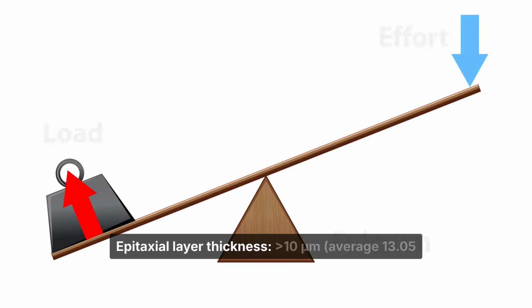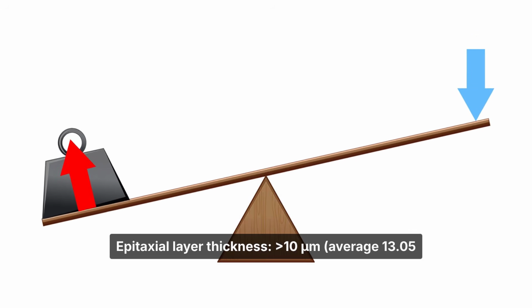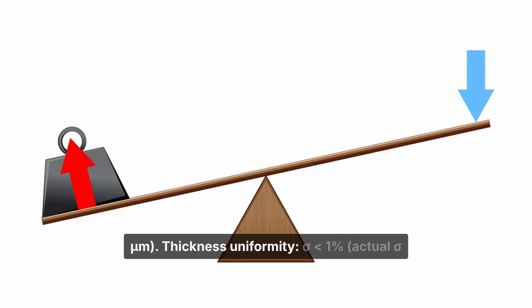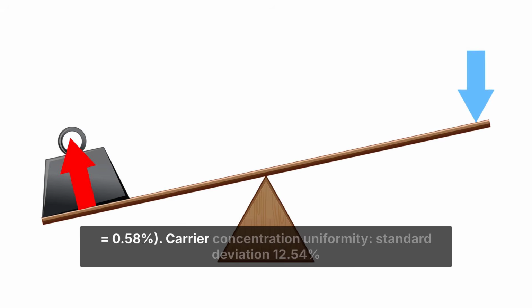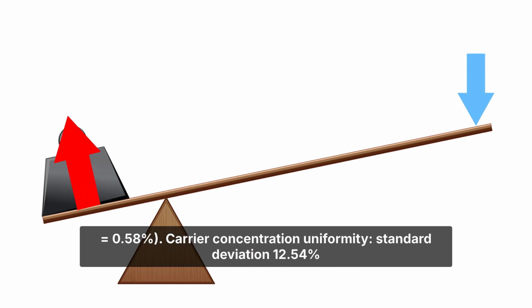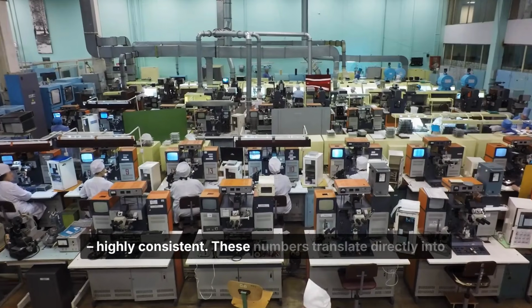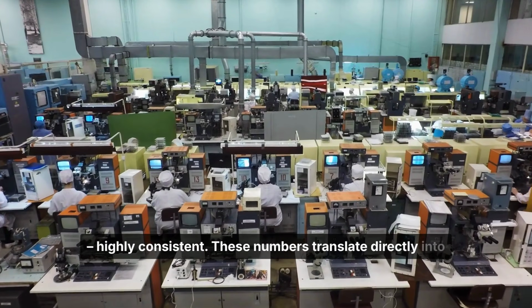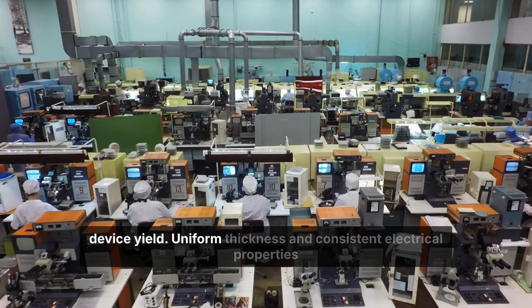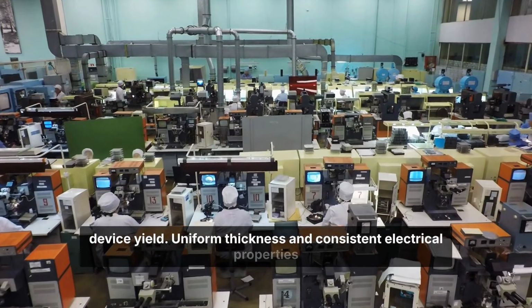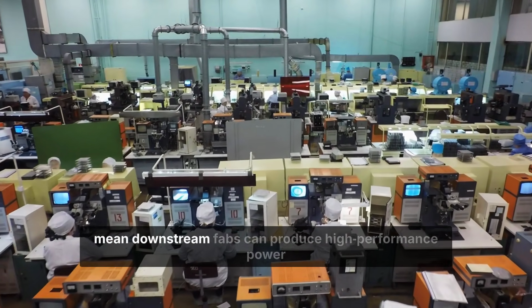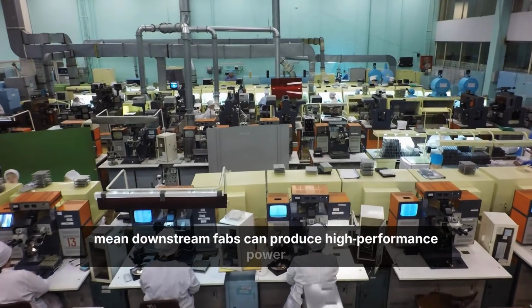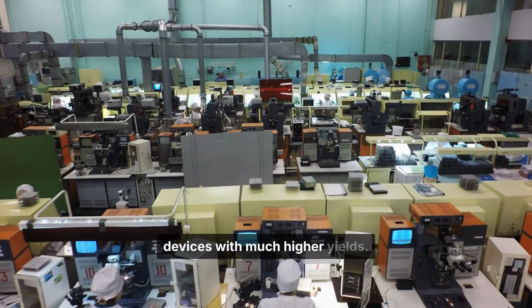Epitaxial layer thickness, average 13.05, thickness uniformity, spec 1%, actual standard deviation 0.58%. Carrier concentration uniformity, standard deviation 12.54%, highly consistent. These numbers translate directly into device yield. Uniform thickness and consistent electrical properties mean downstream fabs can produce high-performance power devices with much higher yields.